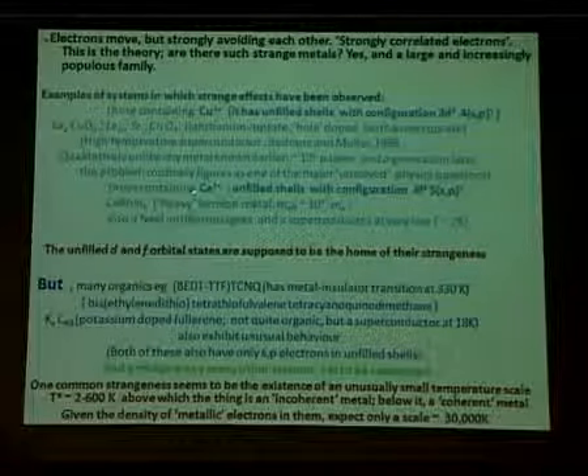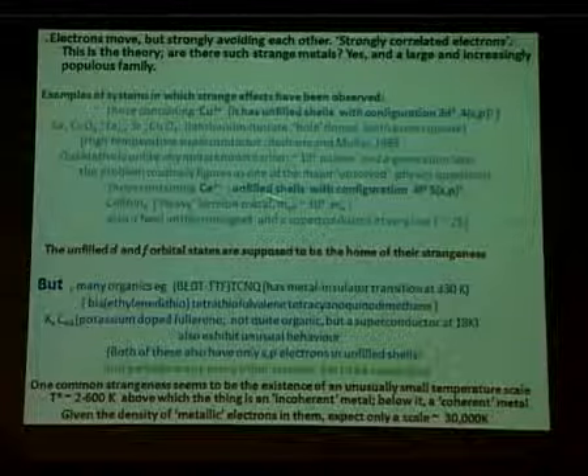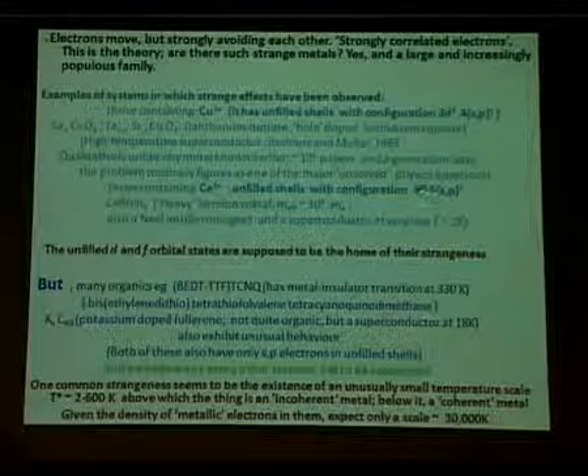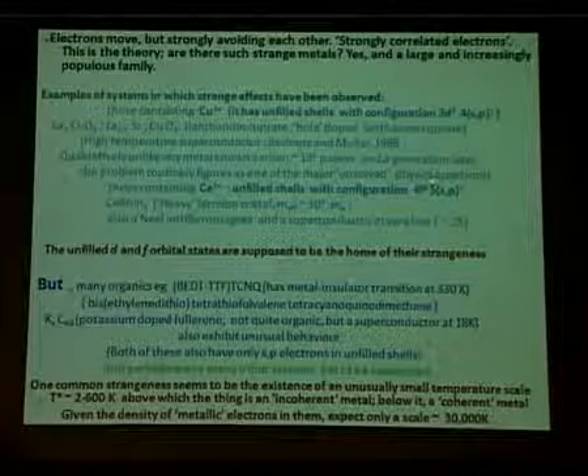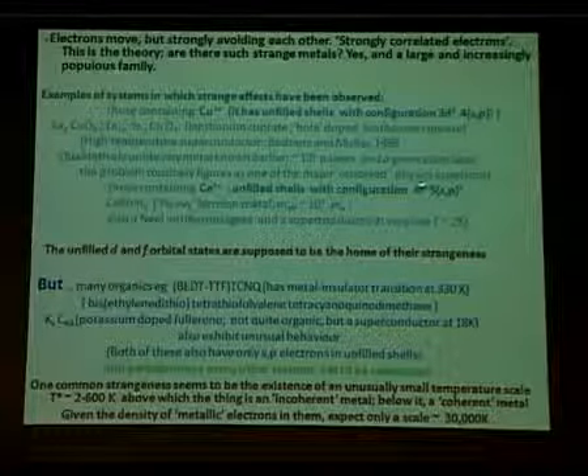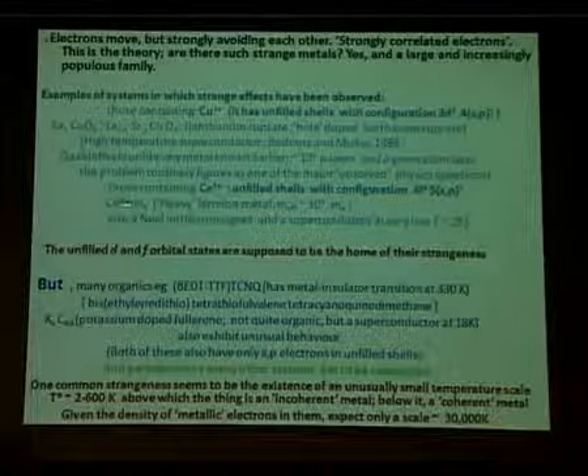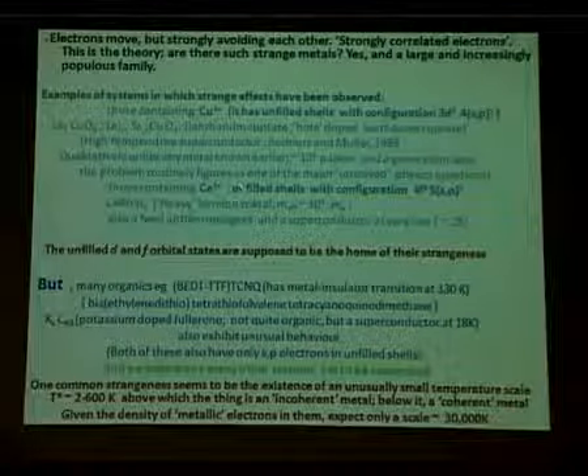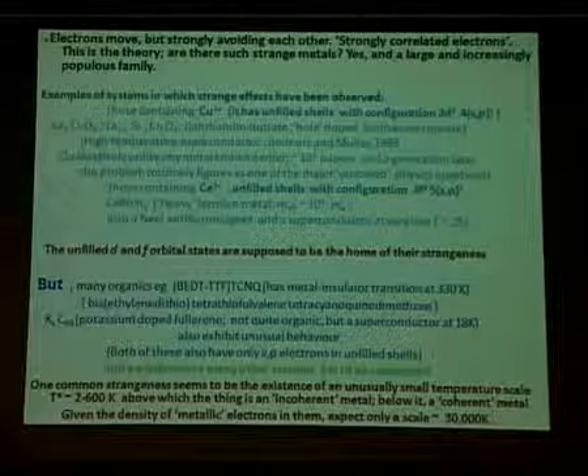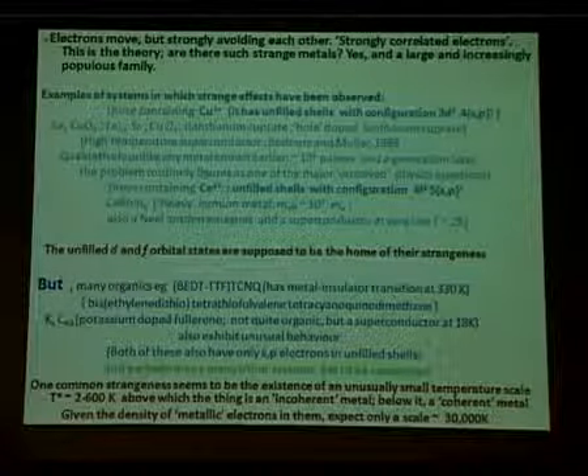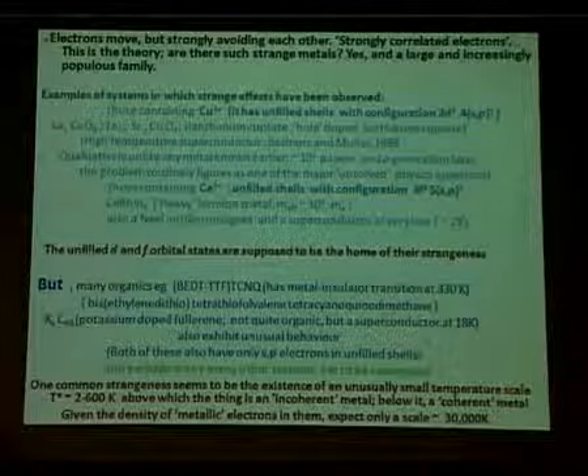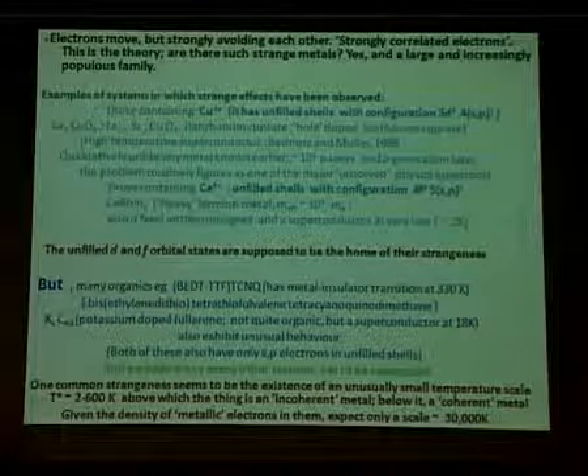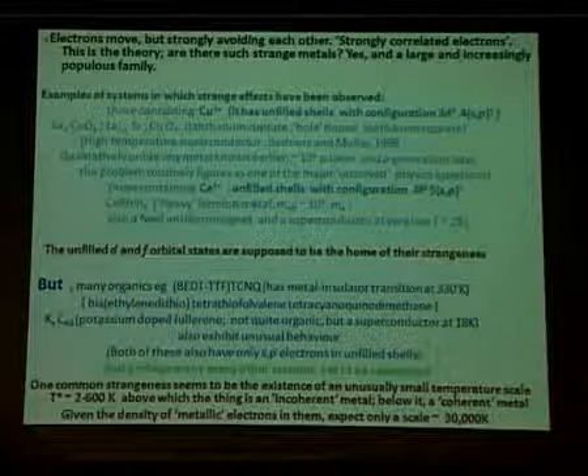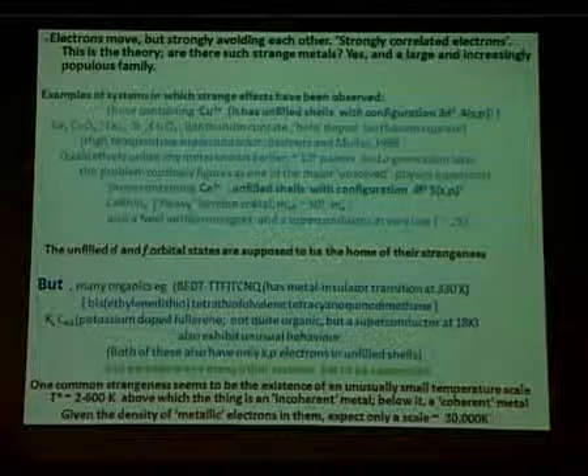There is a similar family of compounds which, for example, contain cerium. And cerium, the electronic configuration is 4f¹ 5d¹ 6s², so there is one electron in the 4f orbital. One example of this is cerium rhodium indium 5. This is a heavy fermion metal. Heavy meaning what? It's not heavy to weigh, but the effective mass of the electrons in these systems is about 1,000 electron masses.